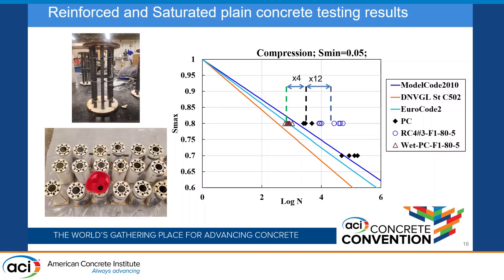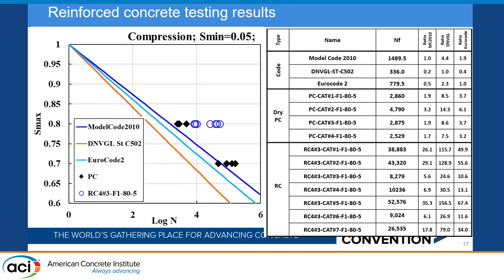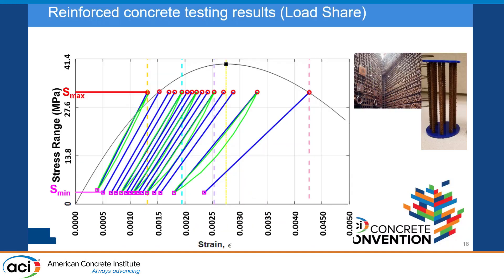For saturation, it is fairly clear that pore pressure reduces the fatigue capacity. For the reinforcement, looking at the stress-strain response of the reinforced cylinder, we see cycles of loading at every 5% increment up to failure. The maximum strain develops faster than the minimum strain, indicating concrete softening, and the load share is changing over time.